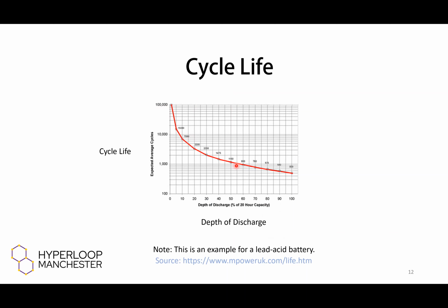This is an example here which is shown for a lead acid battery, which is actually quite an extreme example of degradation, but it relates to the depth of discharge, so how deeply you discharge the battery from its full capacity, or from any capacity really. It doesn't have to be from full, but in this case it is from full, versus the expected average cycles of that. In this lead acid battery, if you discharge to 100%, you can see your battery's only going to last a few hundreds of cycles.